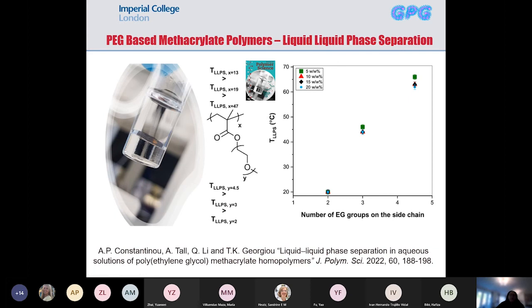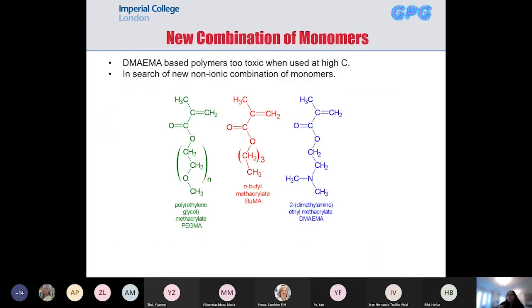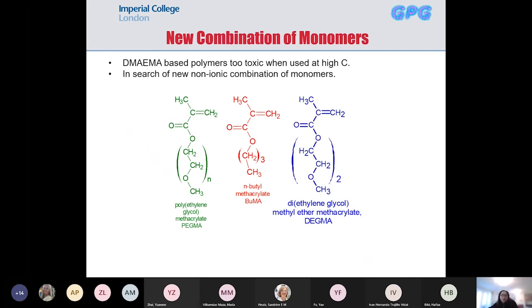So it's often known that if you have two hydrophilic polymers that are both soluble in water, they don't necessarily form a homogeneous solution. Observing liquid-liquid phase separation of homopolymers has been reported before, but this was the first time that it was reported for these polymers. And that liquid-liquid phase separation is dependent on the side group. So coming back to our project, we replaced the DMAEMA group with another PEG-based monomer.